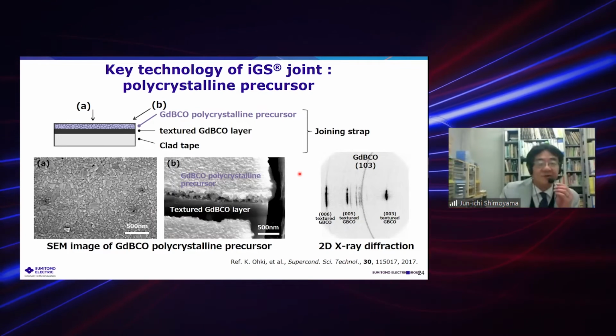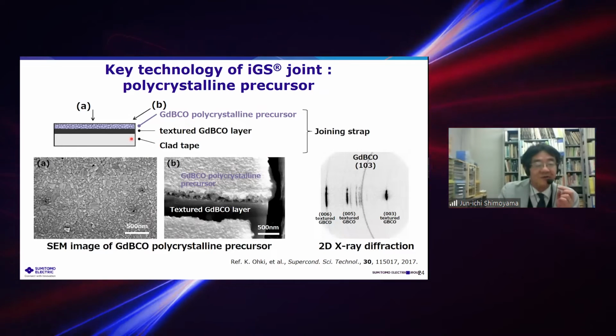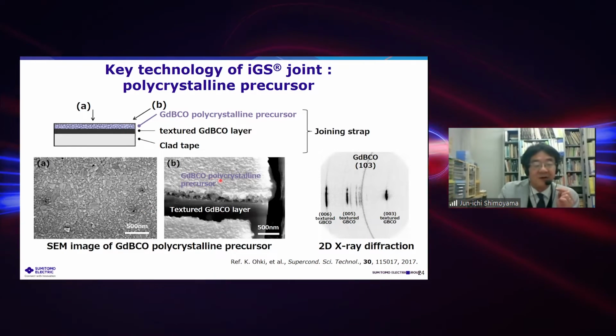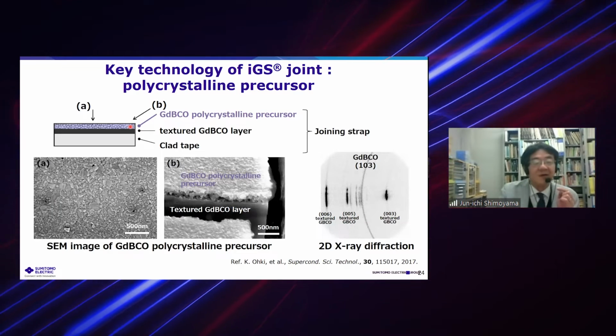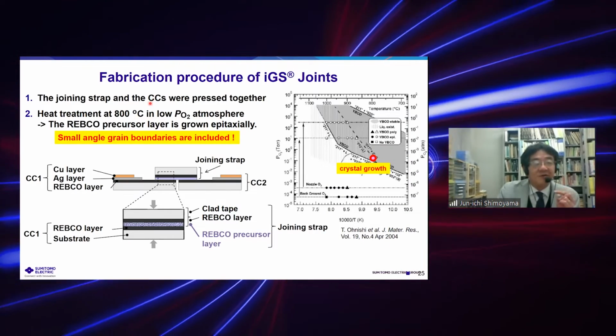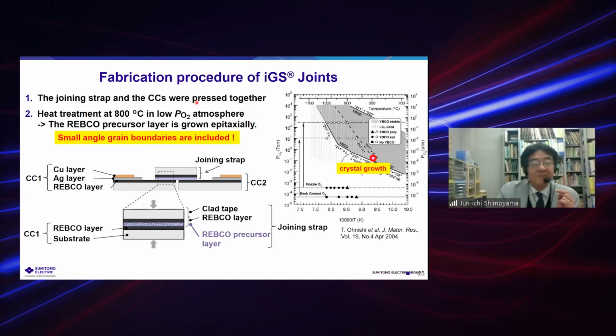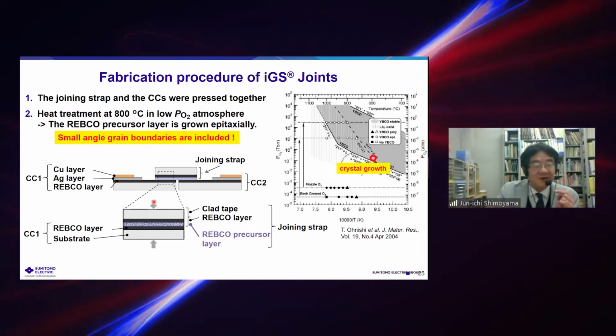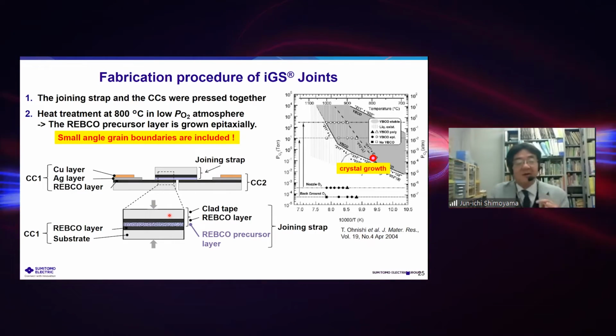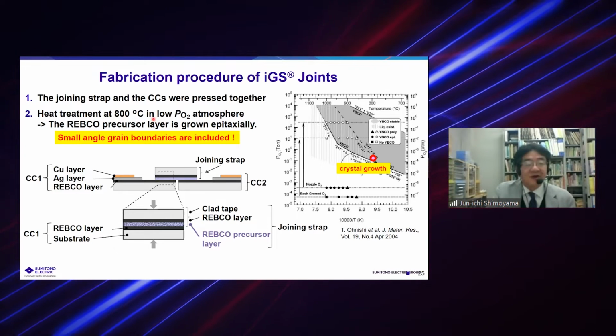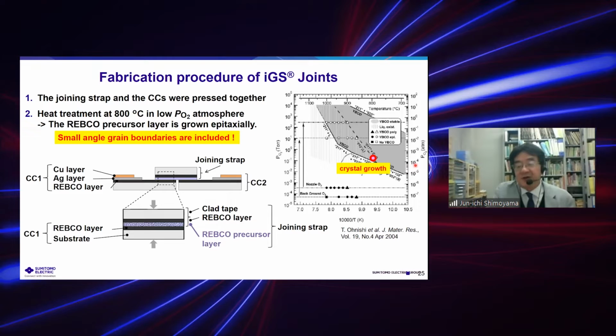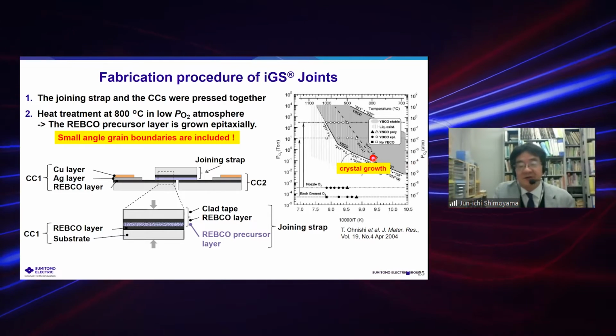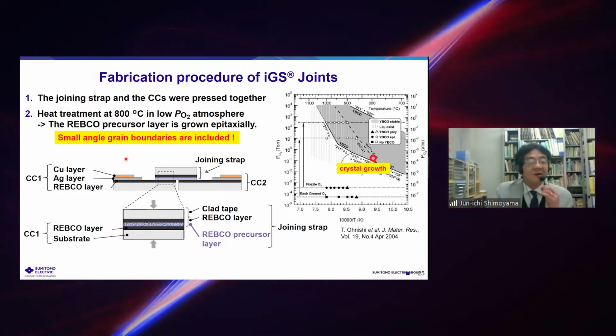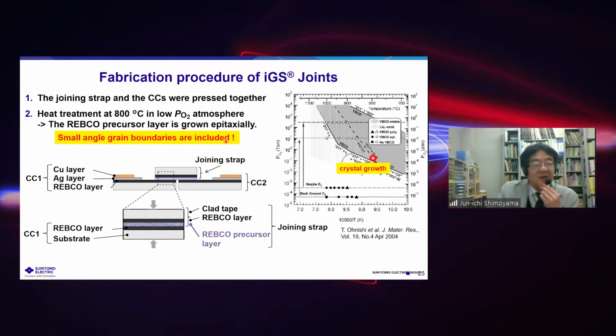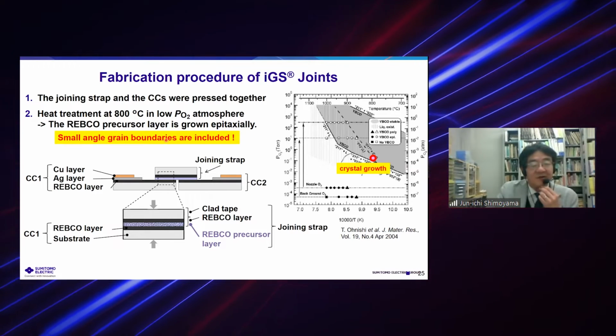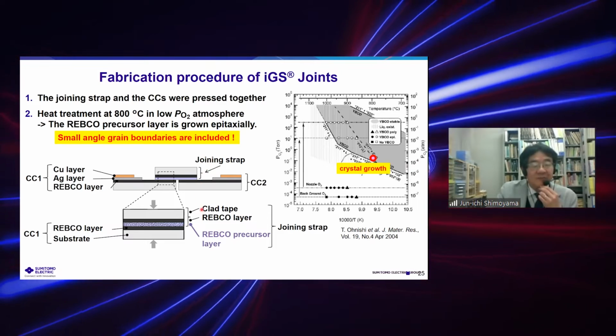Sorry. The key technology of this joint is the preparation of intermediate layers here, a polycrystalline precursor layer on the coated conductors. And the joining strap and coated conductors are pressed together with the intermediate layer, as you see here, at about 40 megapascals. And heat treatment at 800 degrees C in a low pO2 atmosphere, around 10 to the minus 4 atm at 800 degrees C, is the crystal growth condition. The layer grows epitaxially. And an important point is that small angle grain boundaries are included also in the new intermediate layer.